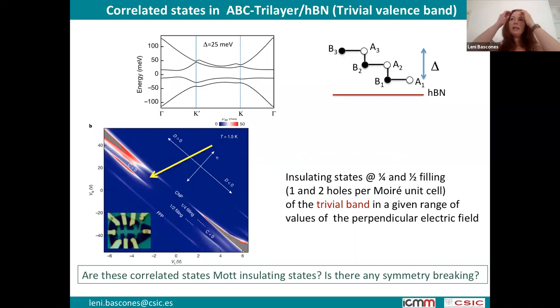This is not just in this moiré, but in all the moiré systems: it's not really clear yet whether Mott physics is important or whether it's much more some kind of conventional band physics. Another interesting question is whether there is any symmetry breaking. And in this system this has become even more important, because recently people have observed very similar results even without the moiré, without the alignment. In fact, they have interpreted that just in terms of Stoner ferromagnetism.